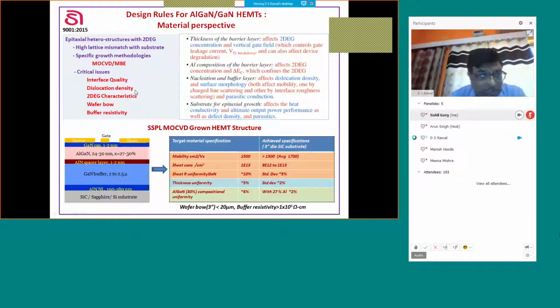Then dislocation density should be very low. Then good 2DEG characteristics mean very high sheet carrier density and very high mobility. Then since these are very strained layers, there are chances that the wafer may curve or get a bow. So this bow should be minimum, because when we fabricate these devices, we are using contact lithography. So we need a perfect contact with the mask. And the other important property is the buffer resistivity. Because this is deciding your leakage current or breakdown voltage of the device, one has to have a very high buffer resistivity. So there are different techniques with which these properties can be obtained, and now at SSPL